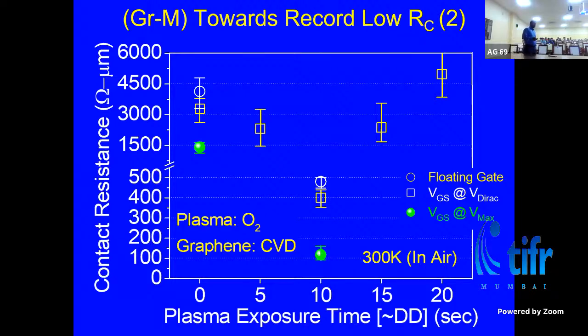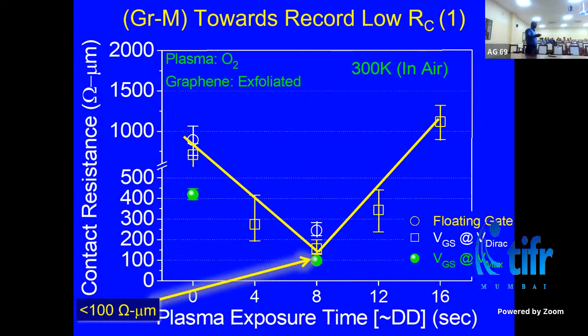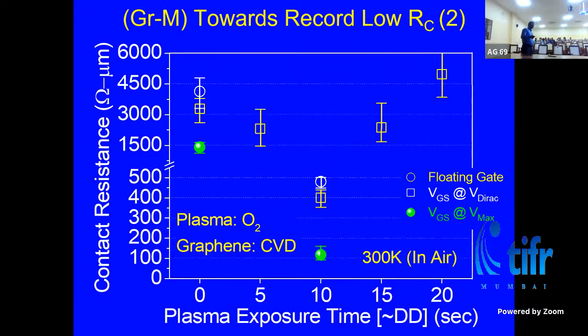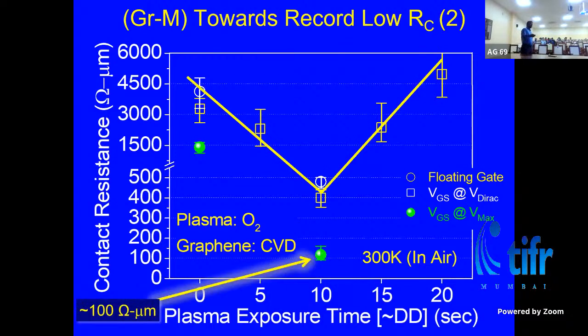Now, so that was exfoliated, right? And in exfoliation, the contact resistance without any engineering is close to 1000 ohm micrometer, right? So 700 to 1000 ohm micrometer is what people typically used to get with exfoliated material, and for exploring a lot of fundamental properties, this was still okay, right? But if you do the CVD, the same thing becomes 3000 to 4000 ohm micrometer. But if you do the engineering, it comes down again to 100 ohm micrometer. So when you have this engineered approach, there's not much difference between exfoliated material versus the CVD material, all at room temperature.